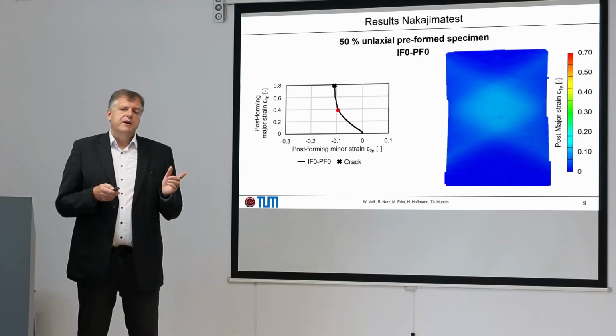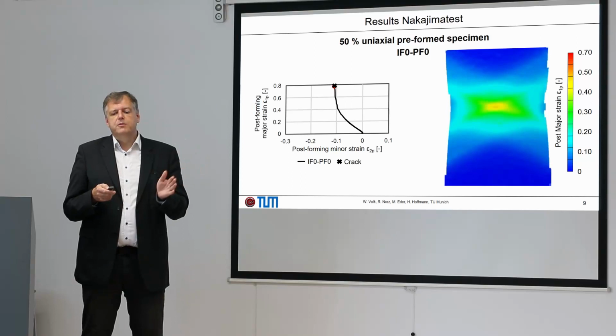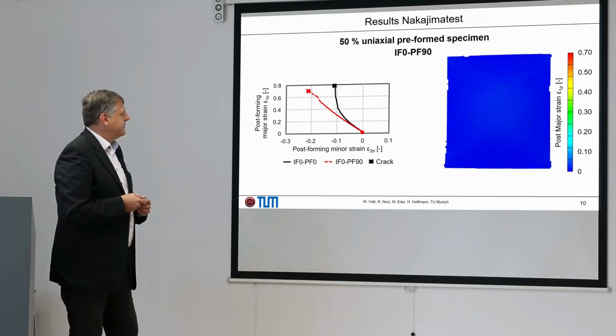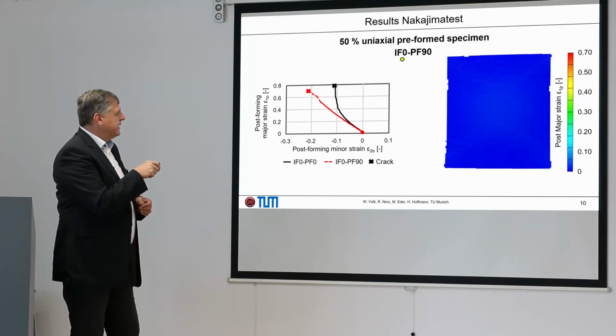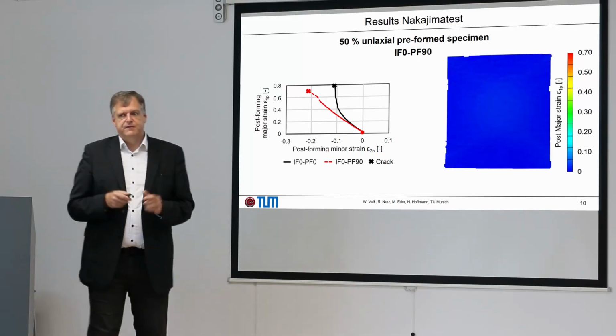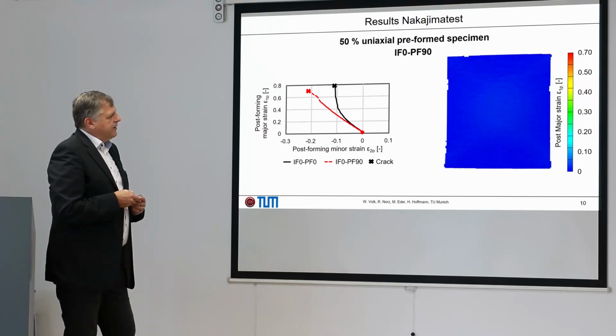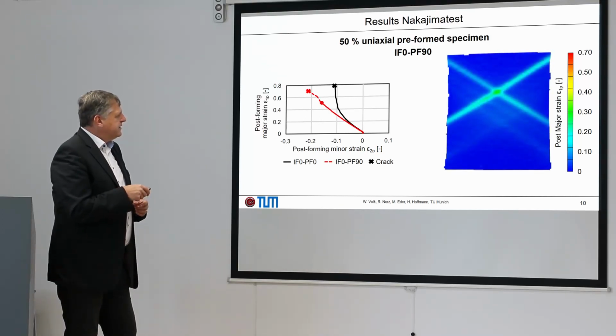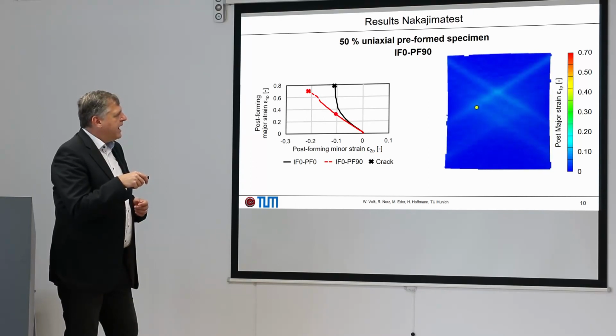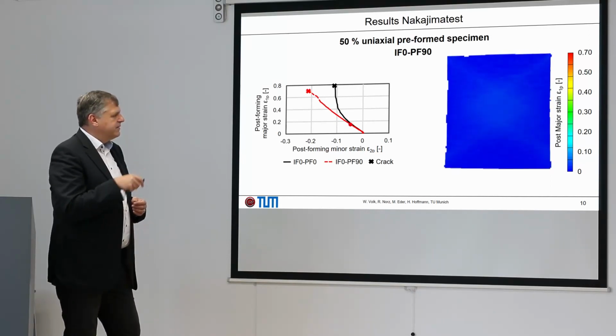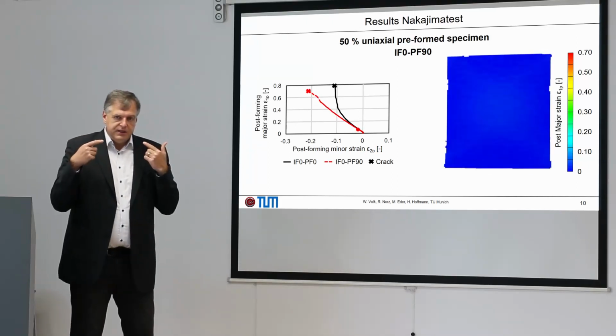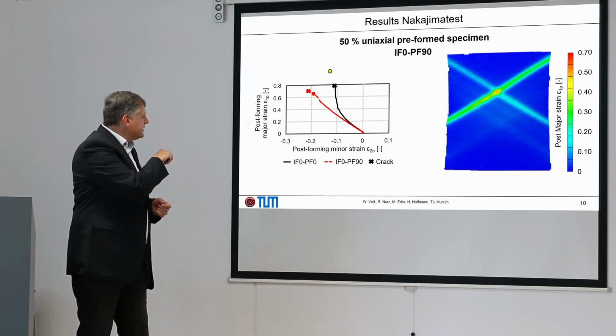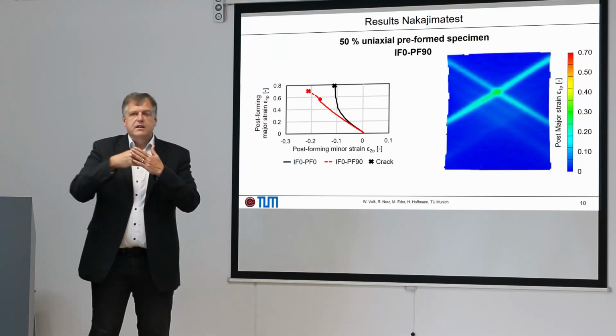And now let's compare with this significantly reduced formability in the 0-90 combination. It means 50% uniaxial preformed, and second step in 90 degrees. It's the red curve. You can directly see here that there is a big difference. When we have a view on the evolution, we see here this surprising effect that we have some kind of localization in shear direction directly after start of the second forming step.